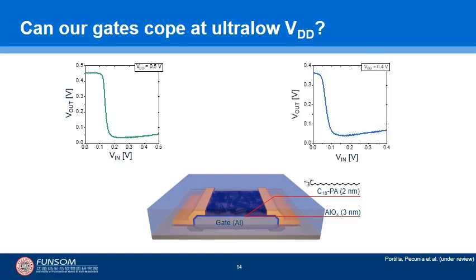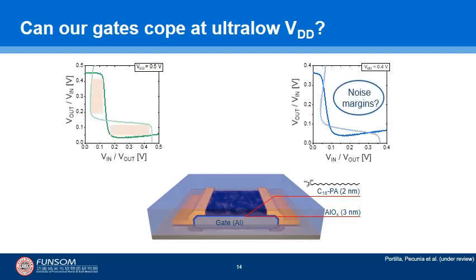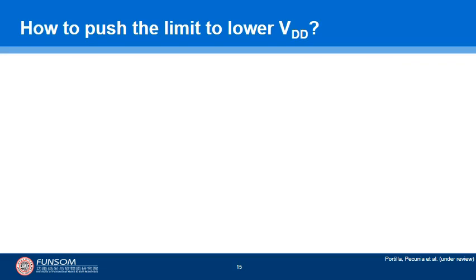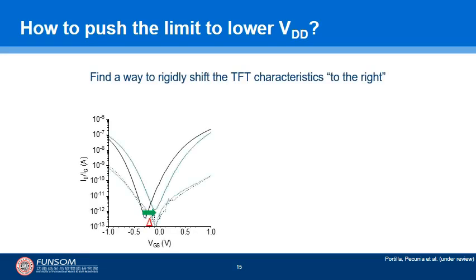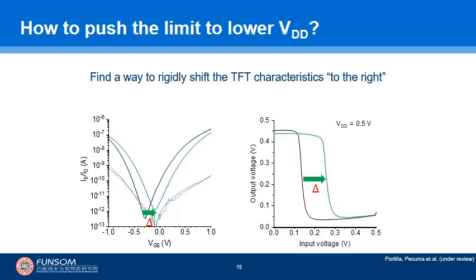But then, when we reduced the VDD to 0.4 volts, the issues with these inverters became apparent. In fact, while the noise margins for VDD equals 0.5 volts are still okay, at VDD equals 0.4 volts, we don't really have noise margins anymore. How could we then address this issue and make our ambipolar carbon nanotube TFT circuits work at lower VDD values? We then thought that if we could somehow rigidly shift our ambipolar TFT characteristics to the right, so to speak, then we should be able to obtain a more balanced ambipolar CNT-TFT input-output inverter characteristic as shown here.